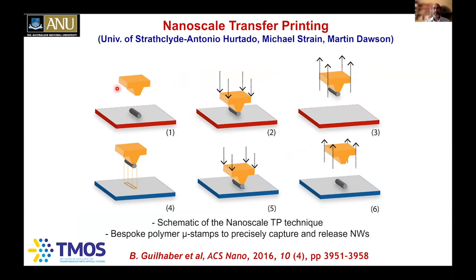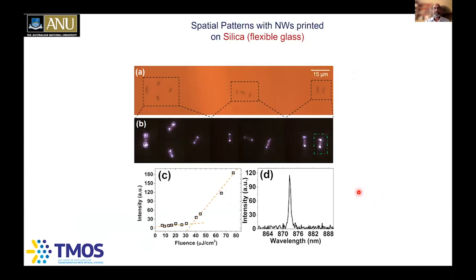In this case, they come up with a PDMS stamp. They can pick up these nanowires and locate them wherever you want, with precise nanoscale location of these nanowire lasers depending on your application. Here is a case where they transferred them onto flexible glass, and you can see 4 nanowires here, 3 nanowires there, 2 nanowires there. We pump them and look at the light emission. You can see light coming from both ends of the nanowire because each nanowire acts like a Fabry-Perot cavity.